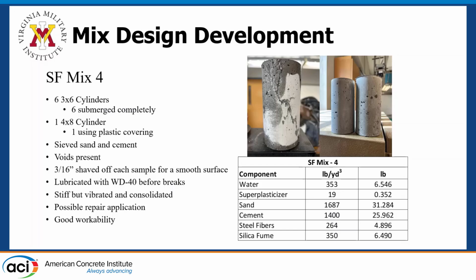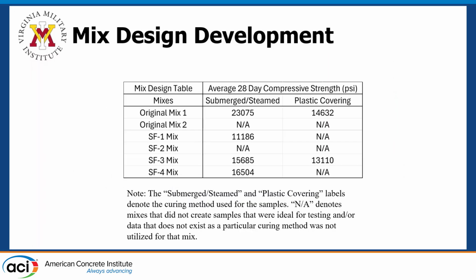So going on, this is our silica fume mix 4. These are 6 3x6 cylinders, 1 4x8 cylinder. This time we actually took very careful and measured approaches of sieving the sand and cement. We had some voids present, but once again, we lubricated with WD-40 before the breaks. It was stiff, but it consolidated well, interestingly enough. So the water content was low, and evidently it was kind of like Play-Doh. It was great to work with, but it ended up consolidating once placed upon the vibrating table, which I found interesting. There's a possible repair application, so it stays in place. It would be great for looking at structures that are like 50 to 75 years old that need that extra set of strength. So here's our 28-day compressive strength. I'd like to point down to SF3 and SF4 mix.